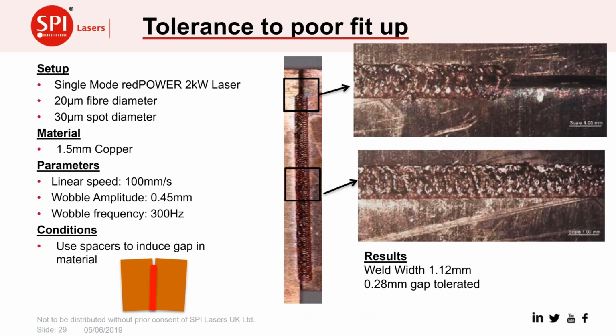This piece, we were trying to show just some tolerance to poor fit up. Remember, this is copper, which is usually very intolerant to gaps in the material. But here we deliberately set two pieces apart with a gap between zero and about 300 micron. As we welded across, we welded up to the bit where it got to a 280 micron gap, and the weld was still going very well.